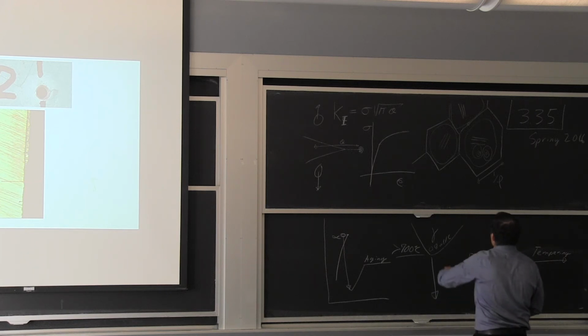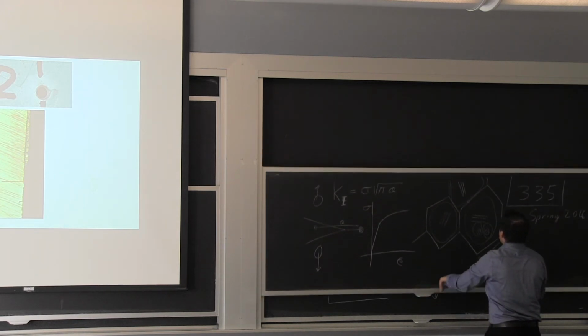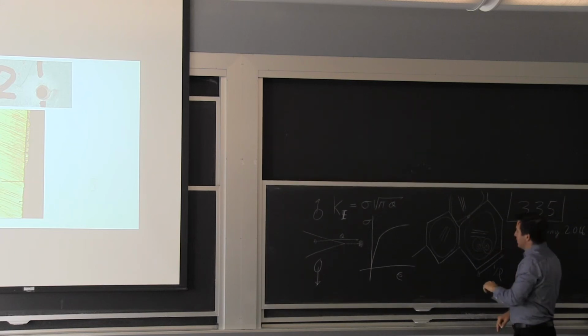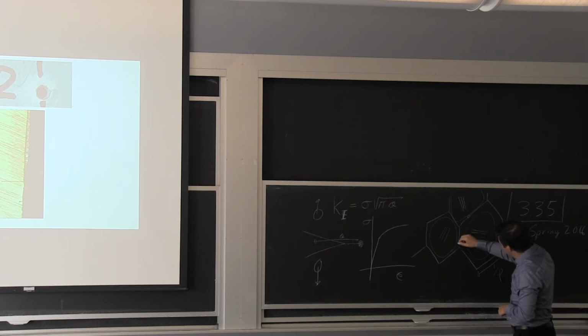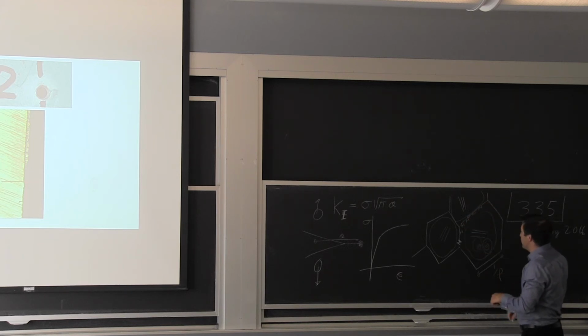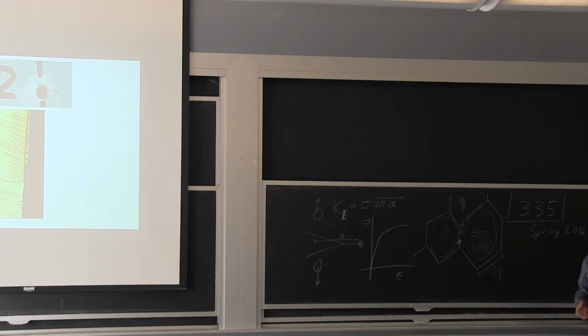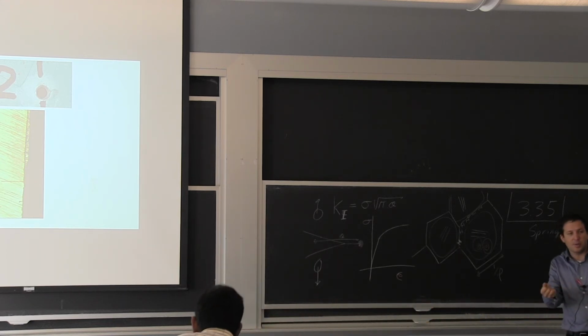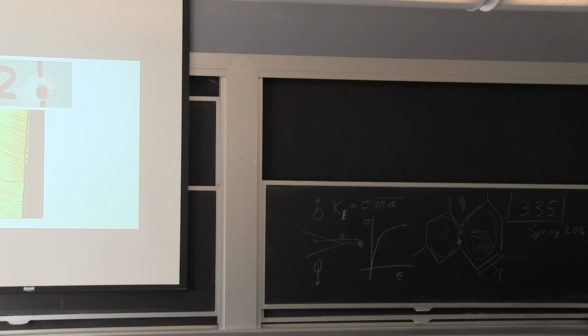If we were talking earlier about this, I said, we got all the deformation taking place here. That's great, no problem. But if I have sacrificial protection of zinc that somehow creates hydrogen, the hydrogen will be preferentially at the grain boundary. It fits in there, and it's reducing the energy of completely separating that boundary. You can think of it, if I put enough hydrogen, it's going to want to form a bubble of gas, right? So to separate between the two grains, especially under high load.